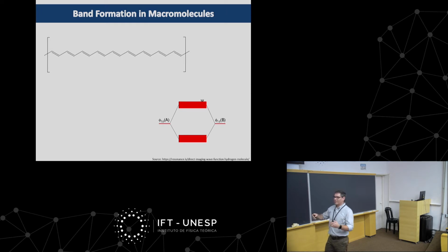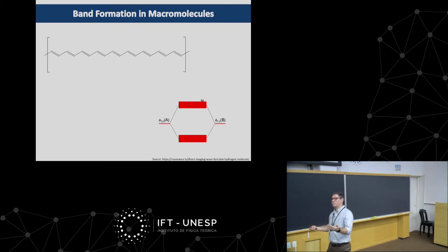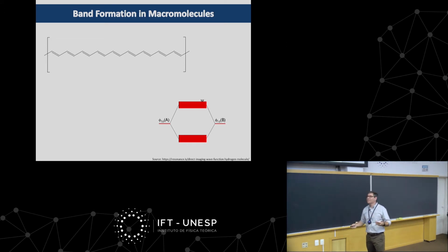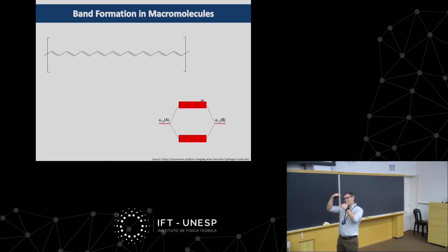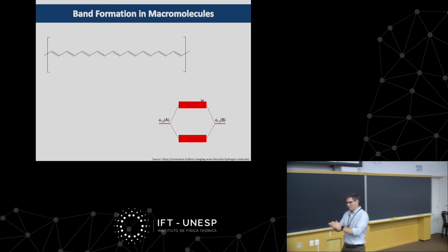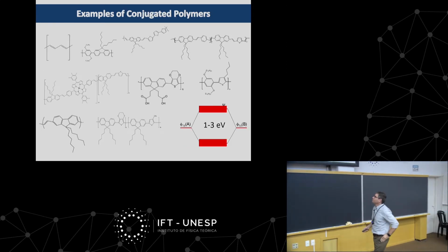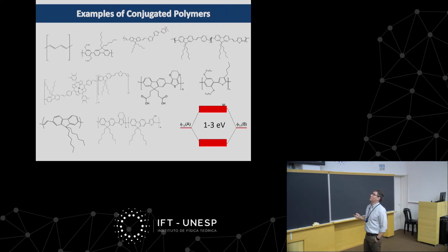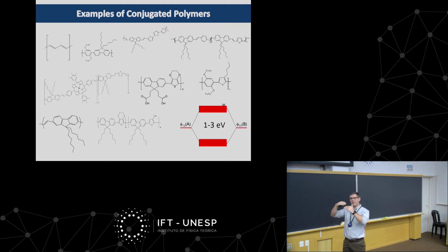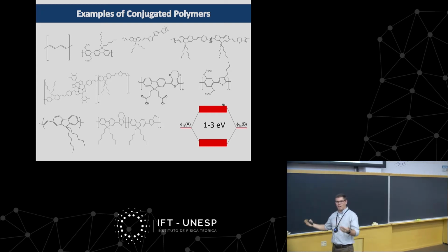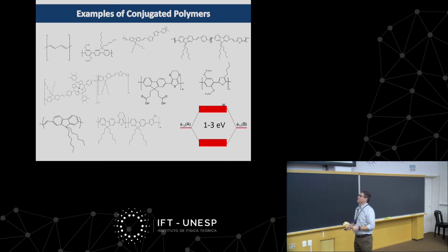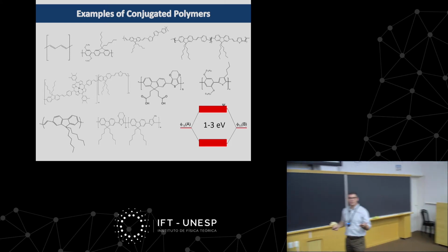And this very long chain, they can actually twist, they can kink, they actually experience different chemical environments, and therefore all those states that were actually very defined in energy become blurry, band transitions where you have very broad transitions going on, okay? And here are several examples of these materials. You can easily synthesize those materials with different synthesis routes, and you can actually pick different molecules, structures, and atoms to tune that band gap, tune crystallinity, tune a lot of the material properties. So that's the reason this is a vast field of research for chemistry as well.